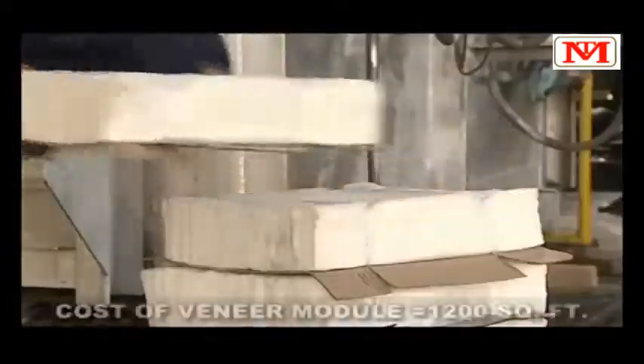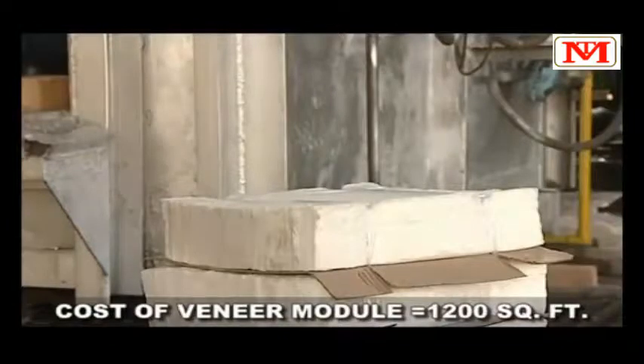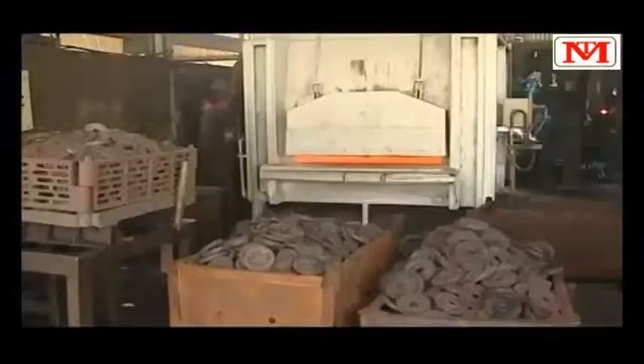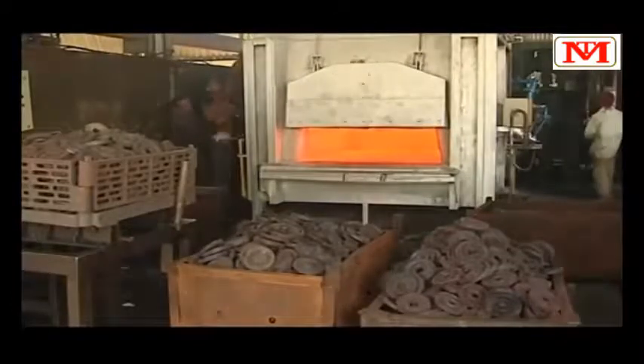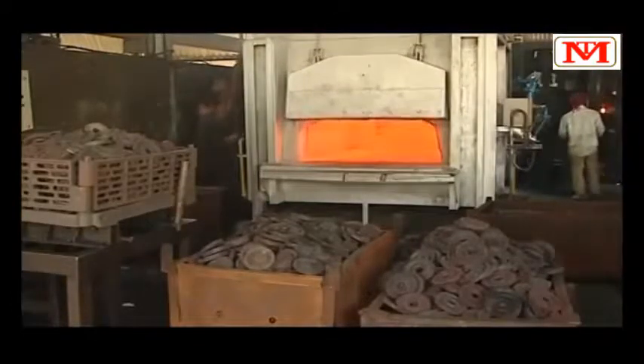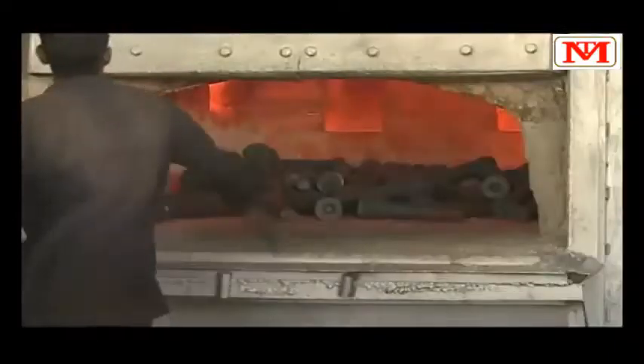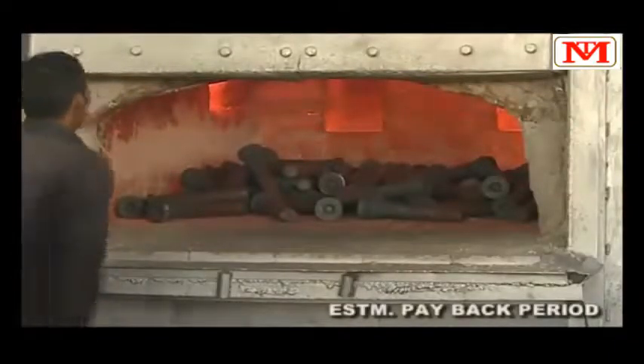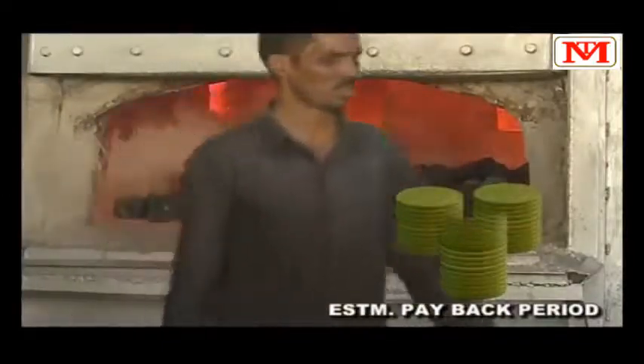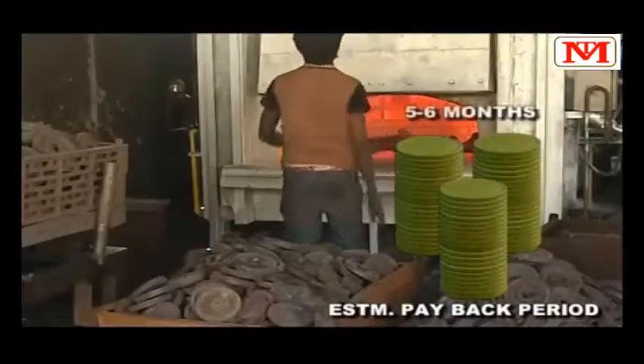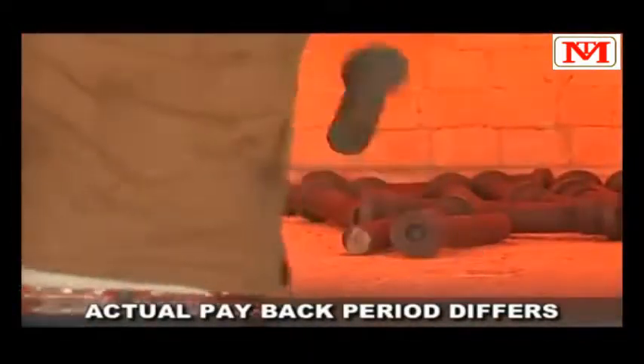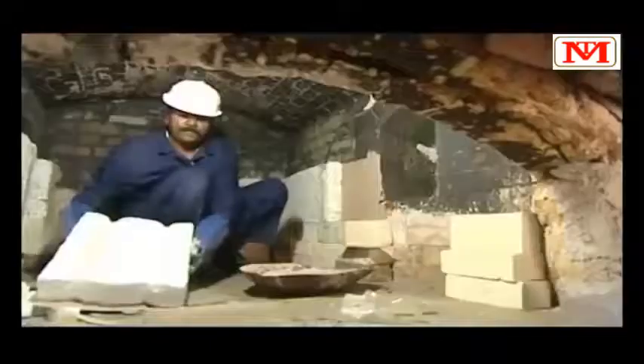The cost of 75 mm thick veneer module is Rs 1200 per square feet. According to calculations, with 225 days of operation and 72 cold starts per annum, the estimated payback period at SB Engineers is 5 to 6 months. However, the actual payback period will differ from unit to unit based on process and operating practices.